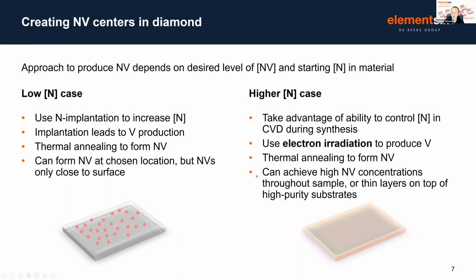If instead we want to create higher concentrations of NV that exist throughout the bulk of a diamond sample, we can take advantage of the ability within CVD to actually deliberately add back in a controlled amount of nitrogen into the process. Then again, as before, we can use electron irradiation to produce vacancies, thermally anneal to produce NV, and through this method, we can produce, if we want to, high concentrations of NV that exist throughout the sample, or alternatively, we can grow high nitrogen layers on top of a high purity substrate and then have comparatively thin homogeneous layers of NV in an otherwise high purity sample.